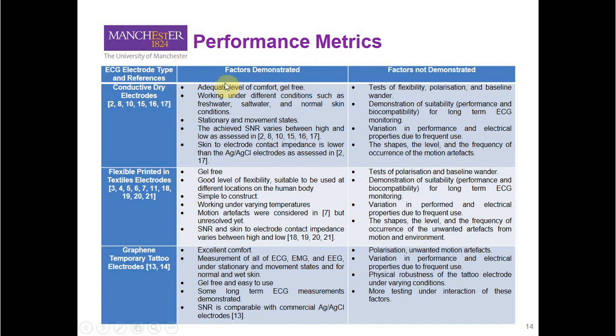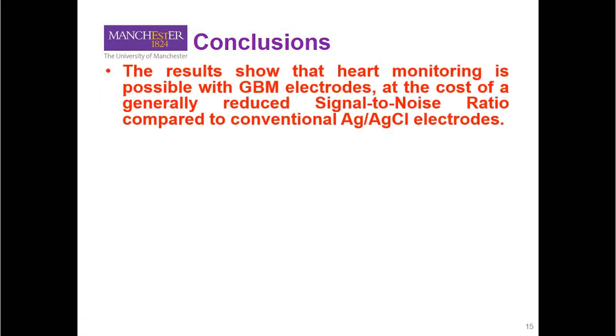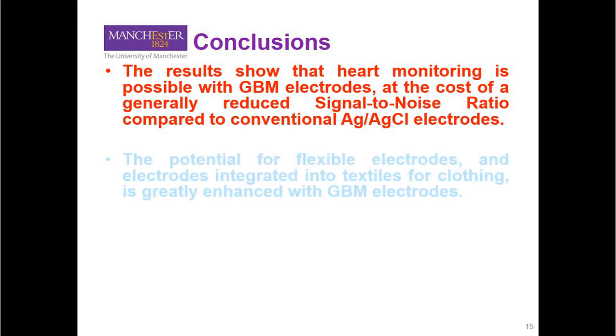This table summarizes all factors demonstrated for each type of those electrodes and the factors that are not demonstrated. I've mentioned some of them, but for further information you can read this table and refer to the references. In conclusion, the results show that heart monitoring is possible with the graphene-based material electrode at the cost of a generally reduced signal-to-noise ratio compared to the conventional gold standard silver chloride electrode.